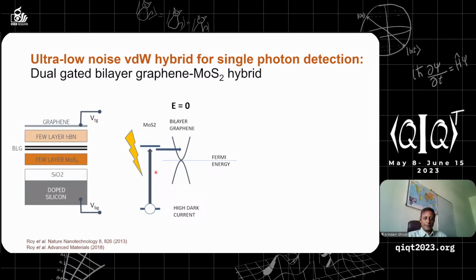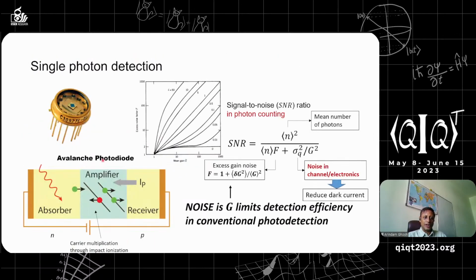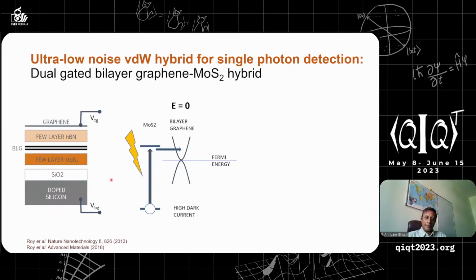So as a result, the conduction region and the absorber region are physically separated. If you look at the conventional avalanche photodiode structure, the absorber region and the conduction region are the same. As a result, you get gain noise because of stochastic recombination. But now, if you create a structure like this, where graphene is sitting on molybdenum disulfide, and you measure the electrical property of the graphene layer alone, then these two regions become physically separated. As a result, the gain noise becomes very, very small. But the problem with graphene is that it doesn't have a band gap. As a result, the dark current is very high, and the noise is very high as well.